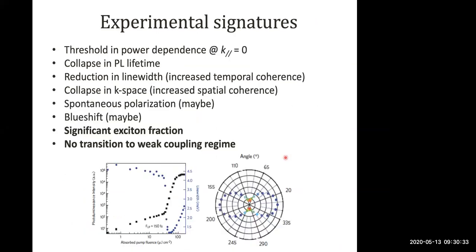Okay, so what are the experimental signatures of polariton condensation? In the power dependence, when we look at emission coming from k equals 0, which is normal incidence, we see a very sharp threshold. This corresponds to the onset of stimulated scattering to that final state. Because of stimulated scattering, you also expect a collapse in the PL lifetime. We have increased temporal coherence and increased spatial coherence at threshold, which we see in the reduction in line width and the collapse in the k-space distribution of polaritons.